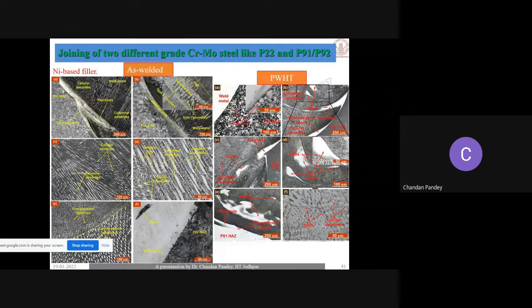Now, again, one problem that we face in case of nickel based filler: we don't require any heat treatment, that is okay. But the nickel based filler is not matching with P22 and P91 steel. So in that case, we get the formation of an unmixed zone, that is peninsula and island, in the region of the weld metal just near the interface. At room temperature, that will not affect the mechanical property of the weld metal. But again, during service condition, that may create a problem.